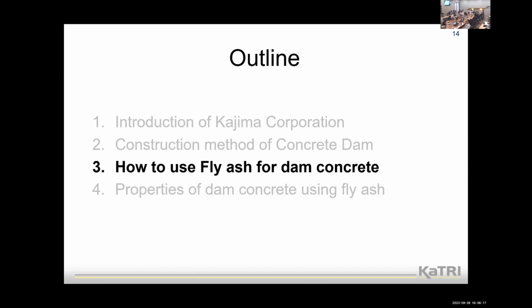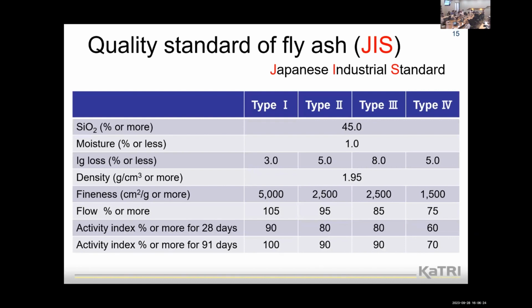And then, how to use fly ash for dam concrete. As Warangkana said, this slide shows the quality standard of fly ash, the Japanese Industrial Standard, JIS. The SiO2, moisture, ignition loss, density, fineness, flow, and activity index target values are decided, and in Japan, fly ash is separated into 4 types. Almost all dam concrete uses type 2 fly ash.